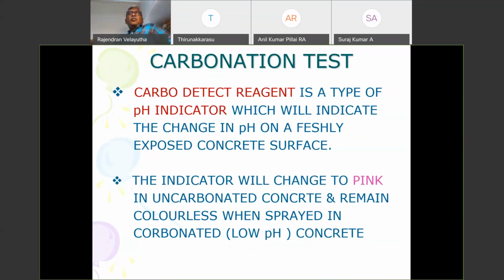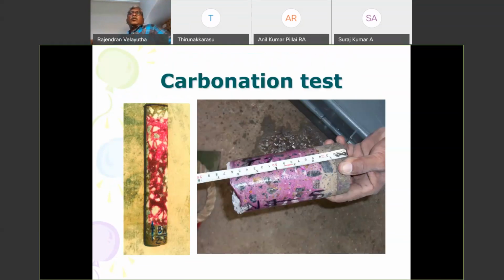This is a very simple test, the carbonation test. I would say that every repair contractor who is going to do the job should have this indicator at site. As he keeps checking the concrete, he needs to spray the phenolphthalein indicator. If there is no change in color to pink, then further he has to chip off. Otherwise, we will not be able to remove the contaminated concrete completely. And keeping the contaminated concrete and then doing a repair and rehabilitation is not advisable.